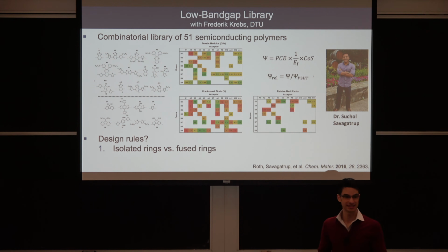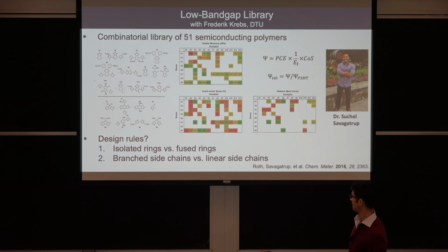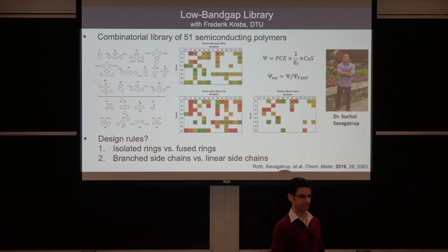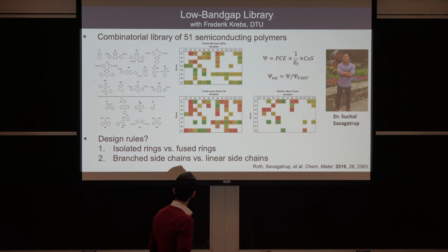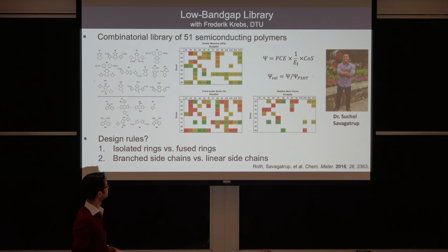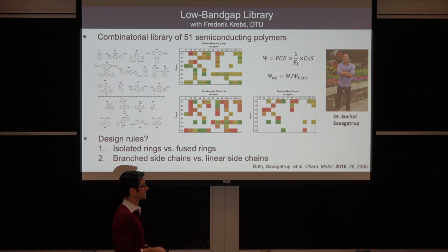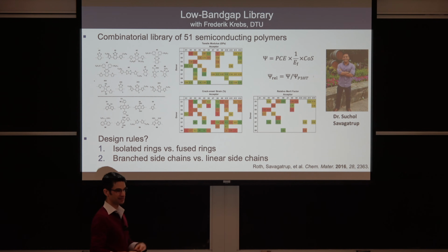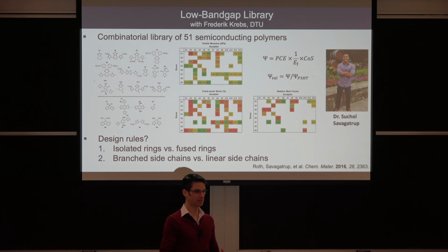So isolated rings tend to give you more flexibility than fused rings, and also branched side chains tend to give you more deformability than linear side chains. Yep. In the title it says there's 51 polymers. Are you showing only a select number? Yeah, the 51 polymers were the ones that were possible to actually synthesize. Some of these materials, because of some idiosyncrasies of the chemistry, we didn't get material.